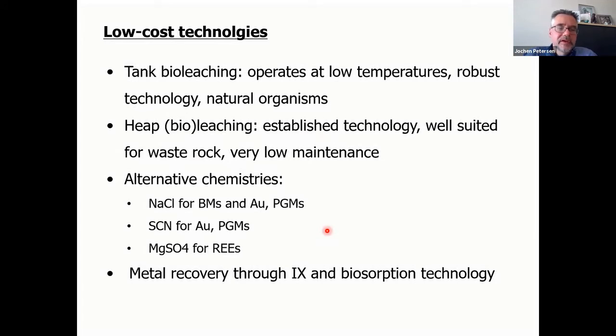There are a number of alternative chemistries that one can also look at. I'm talking specifically here about hydrometallurgical processes, and I guess in a way I've already set myself up to say that for the economic processes in general, you would look more at hydrometallurgical processes, precisely because they can operate at low temperatures rather than the pyrometallurgical high-temperature processes. So you can use different chemistries. The conventional one in most of these processes is sulfuric acid leaching, but here we're looking at other chemistries such as sodium chloride or chloride-rich solutions, cyanide, thiocyanate for gold, which is much less toxic than the classic cyanide, or magnesium sulfate instead of ammonia for rare earth processing. And then, the leaching is just part of the technology because it brings the metals into solution, but you need to recover them from solution as well.